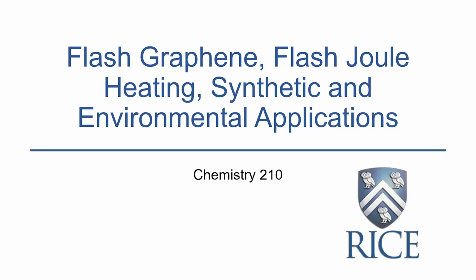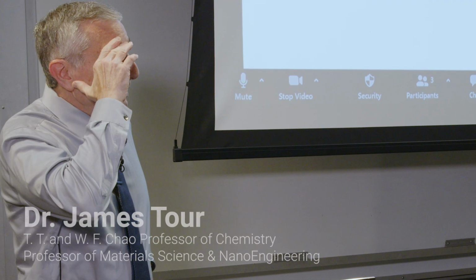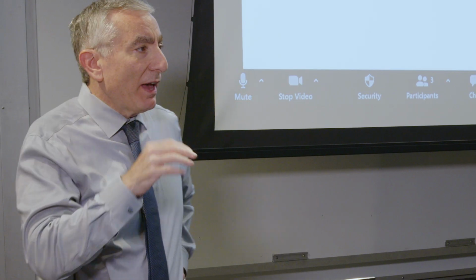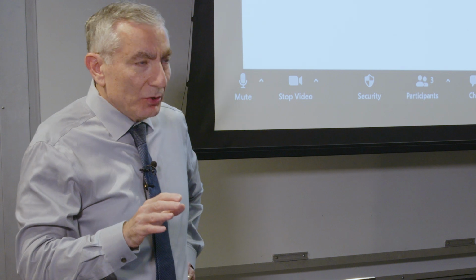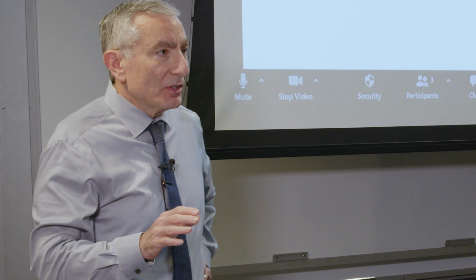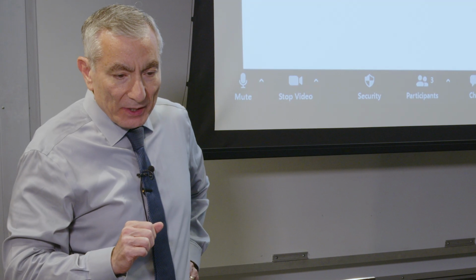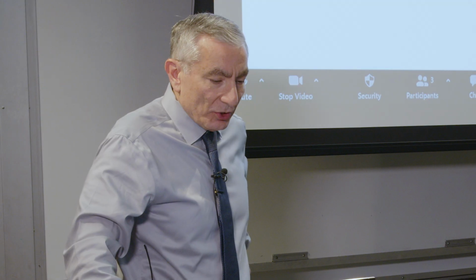We're going to learn about flashing, this flash Joule heating. It can be used to make graphene. This is probably the biggest discovery that I have had in my group. This ability to use flash Joule heating for synthesis. It's really, really big. The extent at which we can proceed with this is really quite large. And what this opens up, I mean, we're discovering all the time what this is going to open up.